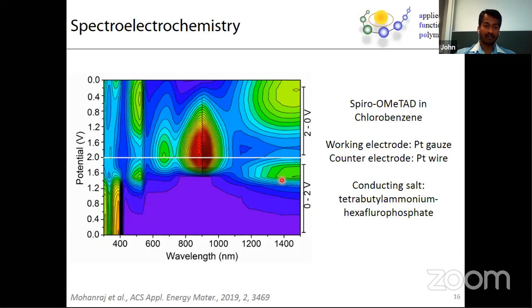On the other hand, when you go higher and higher in potential, then you produce a new molecule or a new system, which absorbs around 650 nanometer as well as about 900 nanometer. And we also checked whether this process is reversible, because you're oxidizing with positive potential. So the system should come back to its original position when you reduce it back to 0 potential, because there is no driving force for the system to stay in the same oxidation state.